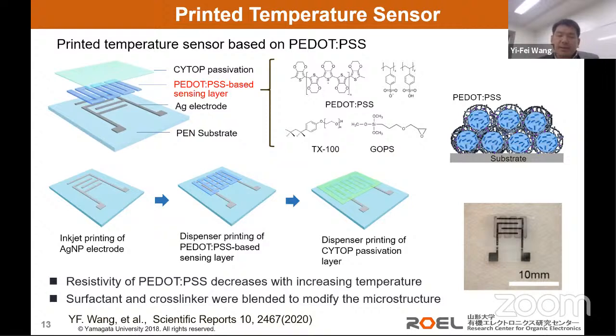So in this case, its conductivity can be influenced by the temperature change. But one of the challenges of the PEDOT:PSS material is that it is a hydrophilic polymer. It's a water-soluble polymer, so it's very easily affected by the humidity in the environment. So in our new ink system, we use a cross-linker named GOPS to enhance its humidity stability. And also we use a surfactant named Triton X-100 to improve the printing property.